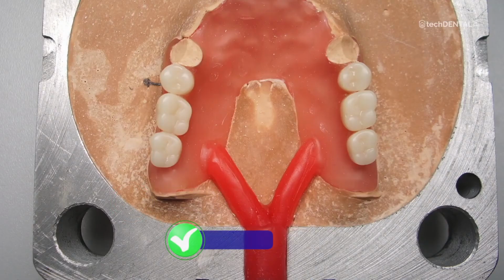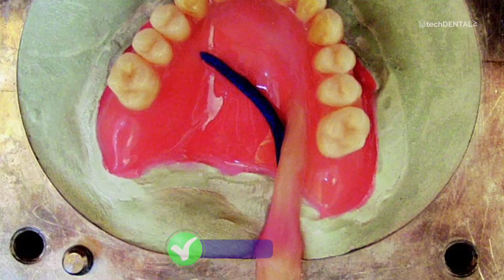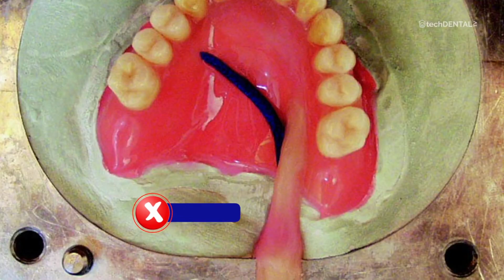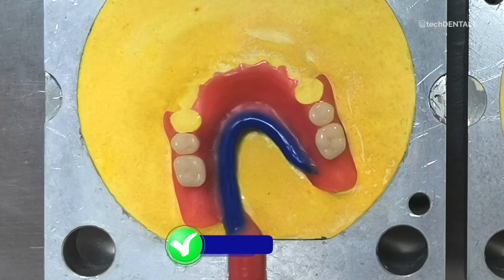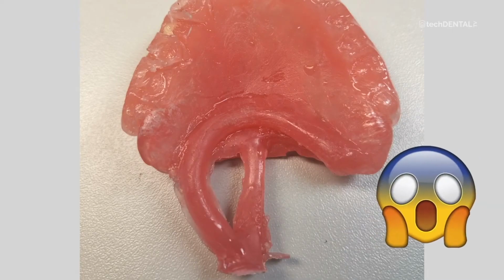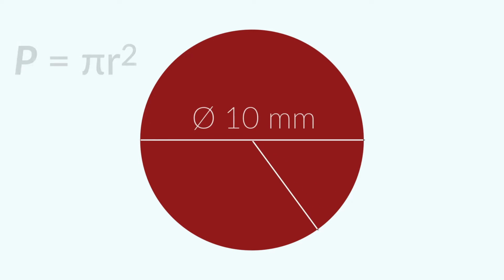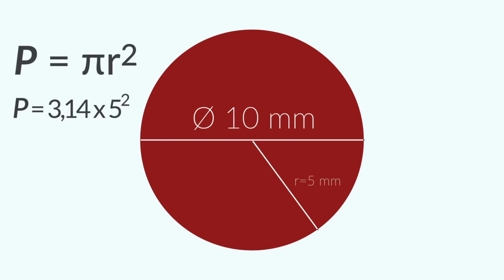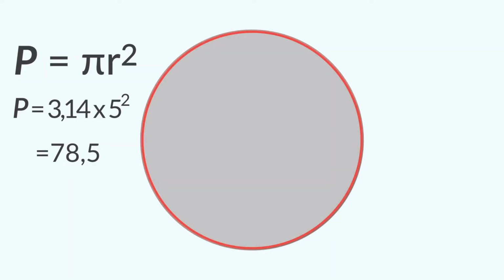The denture model should be as close as possible to the inflow opening. Too much distance increases the loss of material in the channels, and by increasing the flow path of the material to the prosthesis, it increases the risk of failed injection. If you are using two channels, make sure that they have the appropriate thickness. We have to use math in the formula for the area. If the main channel has a diameter of about 10 millimeters, the sum of the channel cross-sections should not be smaller. As a rule, you use channels with a maximum diameter of 5 millimeters.